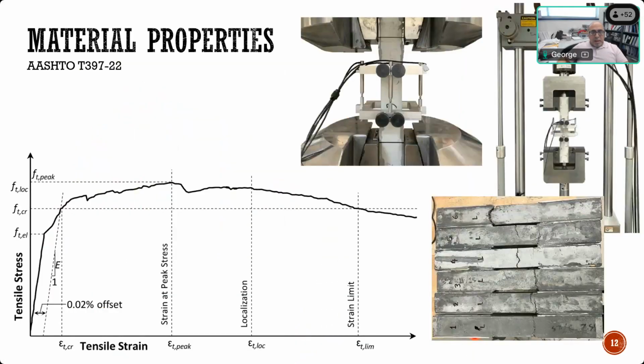Another property that we look at is the tensile capacity. This is a test that was developed recently by the FHWA, and approved as an AASHTO standard test, which is called the direct tension test, in which you make a prism. As you can see here, these are 6 prisms. They are 17 inches long, 2x2 inch in cross section, and you grip it from top and bottom, and you pull this specimen while instrumenting the middle third of the specimen to see the strain.